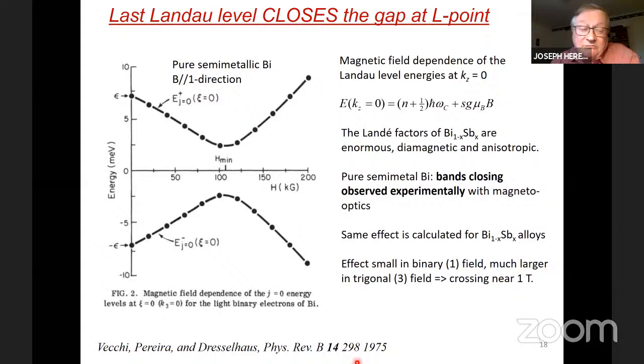Now, I should point out to you that when we apply magnetic field to this, the g factor, which is a g tensor now, can in certain directions of the field become very high, so that the Zeeman splitting term can overwhelm the orbital energy splitting term with high magnetic fields, which means that the last Landau level can actually close the gap. This has been seen optically when the magnetic field was aligned with the binary direction, the 100 direction, but the crossing appears there at 10 Tesla. If we go with the magnetic field in the trigonal direction, the g factor becomes minus 75 or some such number.